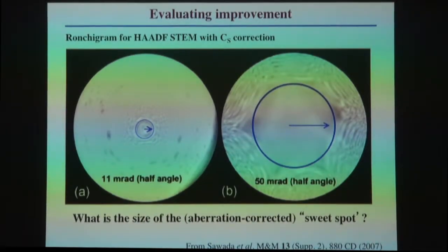So what are the alternatives for you? One alternative is if you have annular dark field, you look at the Ronchigram. And here it's just showing the size of what is called by Krivanek the sweet spot. Here is the Ronchigram without aberration correction. He was only able to get out to 11 milliradians. But once he applied all of the aberration correction, he was able to increase this area where the phase is clearly very uniform out to an angle of 50 milliradians. And so the aberration corrected sweet spot has improved incredibly once the aberration correction is applied.